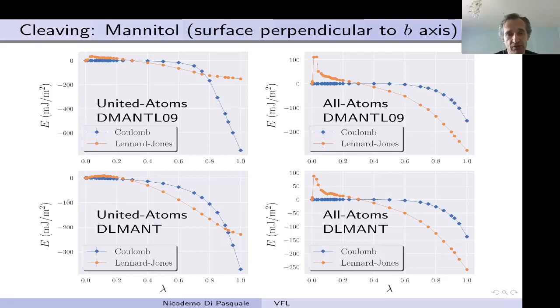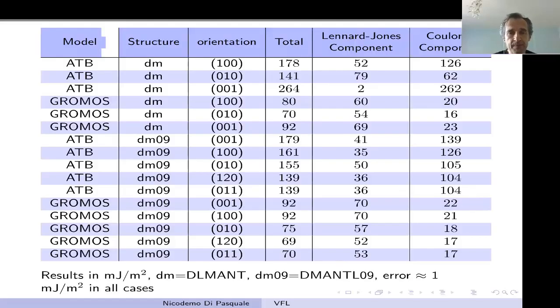We can also separate the two contributions in the surface energy: Lennard-Jones interactions, which could be related to van der Waals type interactions, and Coulomb interaction of residual charges in the models. Next slide, please. And this is the summary of the results that we have so far. They are not yet completely foolproof, so we're still checking whether there could be any errors that need to be fixed.